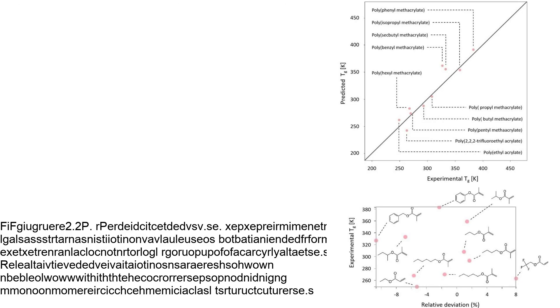The figure presents the predicted Tg values obtained from the trained ANN compared to the experimental Tg values for the external control group of polyacrylates, along with the relative deviations between predicted and experimental values. The ANN shows good agreement with experimental Tg values, with mean absolute percentage errors of 4% for the training set, 8% for the validation set, and 4% for the control set. The relative deviations in the external control group are within a 10% margin, indicating the accuracy of the ANN in predicting Tg based on chemical structure.